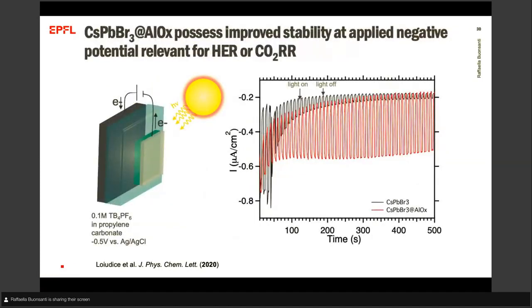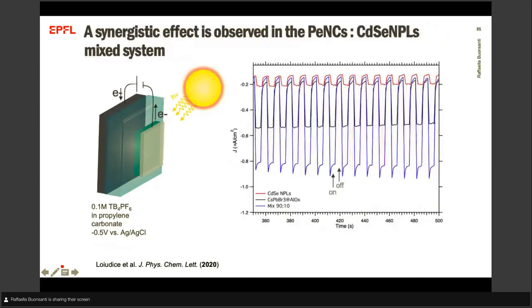We also proved that in conditions that are usually utilized for photoelectrochemical CO2 reduction, these quantum dots in the presence of the shell are much more stable compared to unprotected quantum dots. And also, interestingly, the photocurrent that we measure when we have the mixed quantum dots, the cesium lead bromide and the cadmium selenide, is much more than the sum of the isolated components, indicating also here that there is some synergism between the two of them.